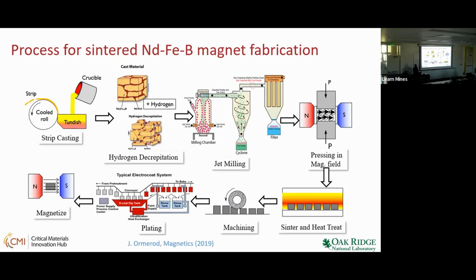Then once you have the jet milling and the powder size you need, you are going to align it in a magnetic field. So you are aligning, pressing, more like compressing, and going through the sintering and heat treatment. The heat treatment process is here, a long duration, very slow. Then you will do the dysprosium and terbium grain boundary diffusion. So that's the process, it may take a while.